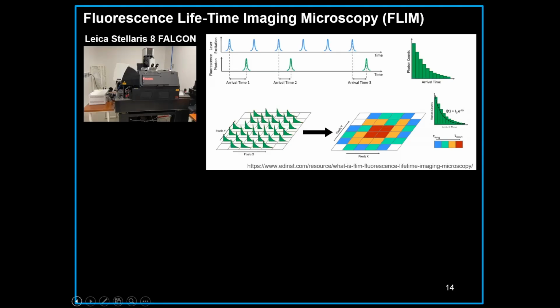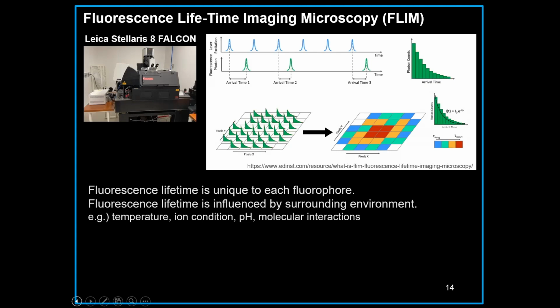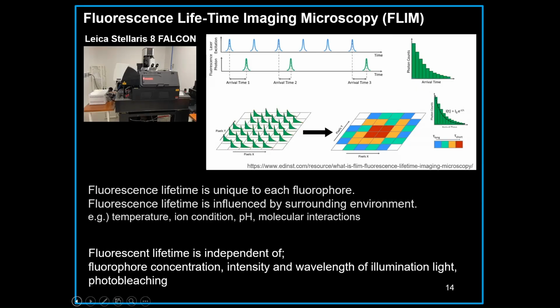So if the fluorescence lifetime is short in a certain area, it shows red. And if it has longer fluorescence lifetime, then it shows greenish blue color. And if no fluorescence photon is counted, then it will show black. Oh, here it's white, but it's going to be black. And what is fluorescence lifetime? Fluorescence lifetime is unique to each fluorophore. It can be influenced by the surrounding environment like temperature, pH, ion conditions, and molecular interactions. But it isn't affected by fluorophore concentration, the illumination wavelength used, or whether it's photobleached or not.